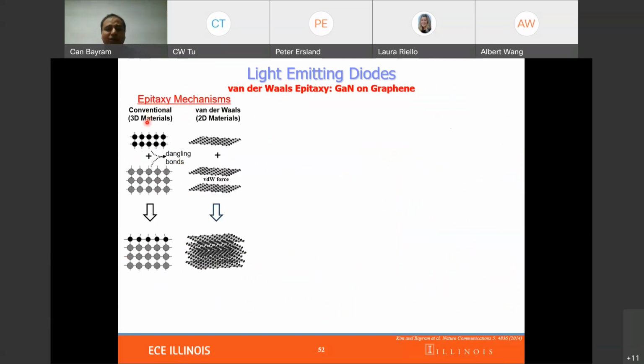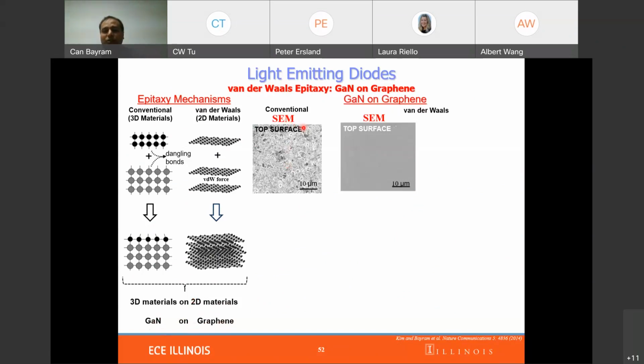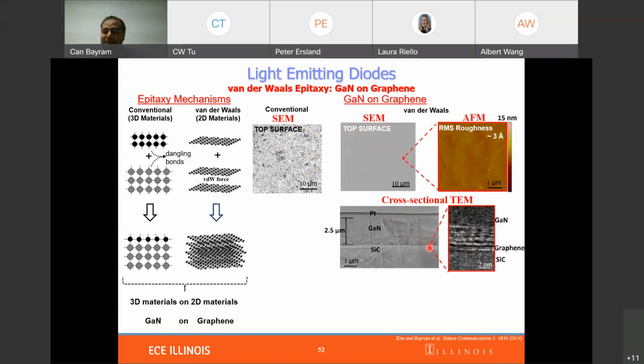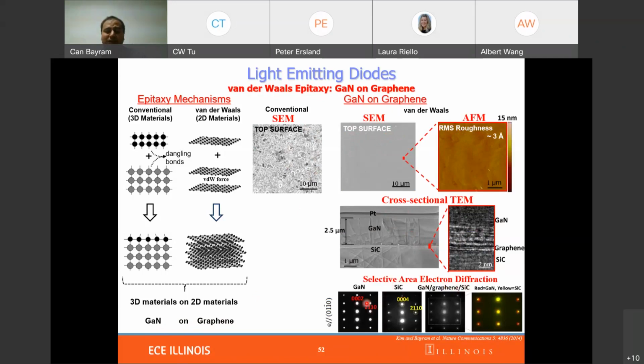The conventional epitaxy of 3D materials depends on the dangling bonds and the bond interactions. The van der Waals materials interact with the weak van der Waals force, and you can stack them layer by layer. So what I'm going to show you is a new technique, 3D material on a 2D material, in the case of GaN on graphene. If you try to grow GaN on graphene directly, this is how it looks: multicrystalline and non-uniform. We have come up with a process to grow a single crystal structure on top with roughness which, as you can see here, is very smooth. We proved that the graphene is still intact by high resolution TEM studies, and graphene is still at the interface. And by selective area electron diffraction, we have shown the crystallographic relationship between all these structures.